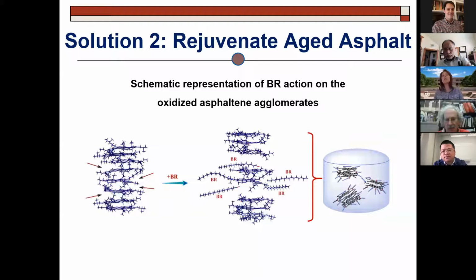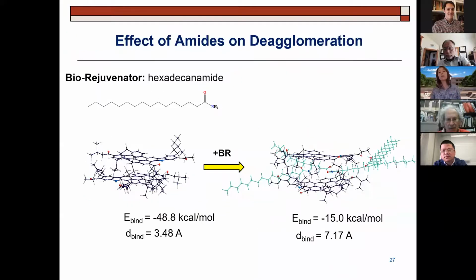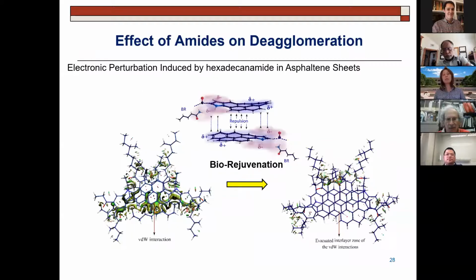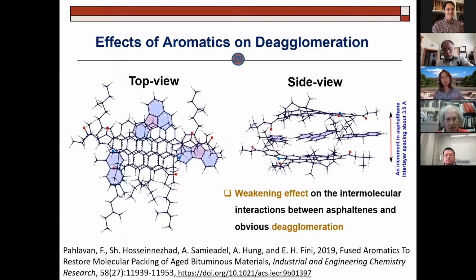I'm just physically changing the conformation of the molecules so that they are not stacked in the same way. And so this bio-rejuvenator can get the energy reduced also. You can see from 48, now we are back to -15, which is the bonding of those. They're not going to agglomerate as much because we got bio-rejuvenator in between. Same thing with this. It's a bit more on the DFT side, but the overall message is that bio-rejuvenator can get within the agglomerate and break them apart.